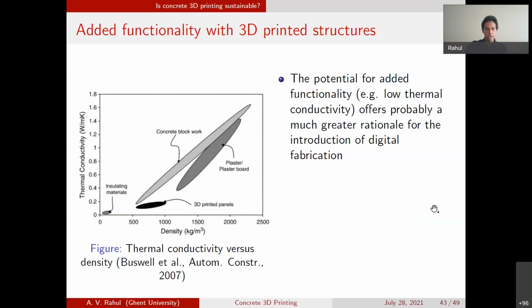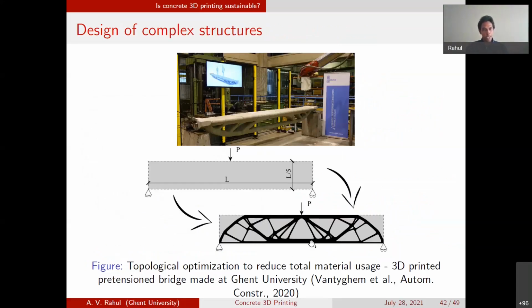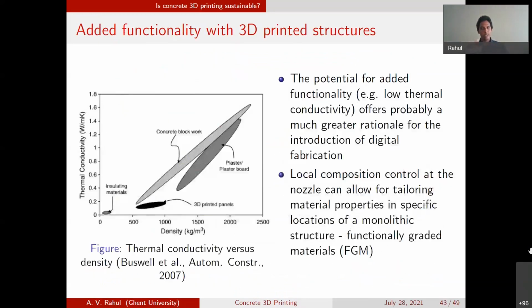Say, for example, if you go back to this situation, in these regions where there is high demand for higher structural performance, you can use a high strength concrete, and in the other regions, maybe we can use a lower strength concrete, which is more economical and has a lower binder content. So this local composition control being integrated is one of the significant advantages that's possible with 3D printing. And this can then, as I mentioned, be used to make functionally graded materials.